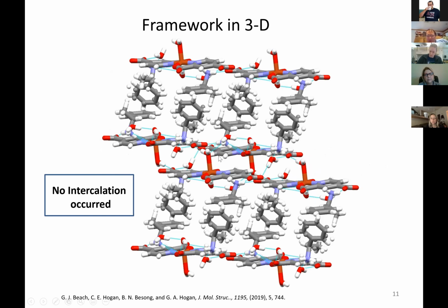Now, this one looks different from some of the previous pictures because it actually formed what's called a bilayer. As you can see, you have 2 adjacent layers right on top of one another. A little bit different than what we've seen. Very interesting, and we're going to come up with a little conclusion and a little theory on this later on. But not a big deal. It's research. The next thing is that inside this crystal structure, we had no intercalation, so there's no guest inclusion. This is just the methyl benzylamine that formed our interlayer, and there are no extra molecules.